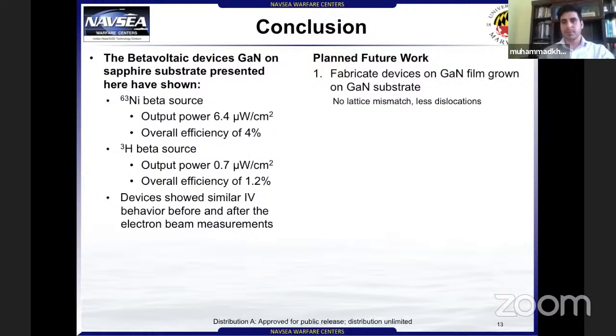In the future, we want to fabricate our devices on GaN, which will be grown on top of a GaN substrate. There will be no lattice mismatch as in the previous case, and there will be fewer dislocations. And we want to optimize our intrinsic layer to 500 nanometers, which I talked about in the previous slide.